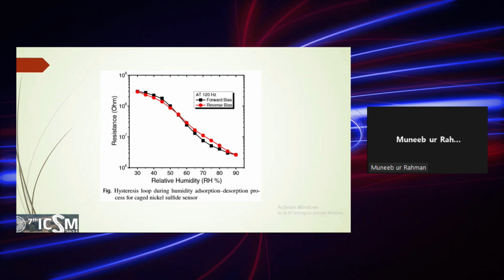This is the hysteresis loop for the sensor. When we increase the humidity inside the chamber from 30% RH to 90% RH, the resistance of the device decreases, which shows a semiconducting behavior. This is also observed with the temperature effect. So we noted that it behaves like a semiconducting material. But in this case, as we know, there is a hydrogen H plus ion contributing, hopping from one molecule to another molecule.